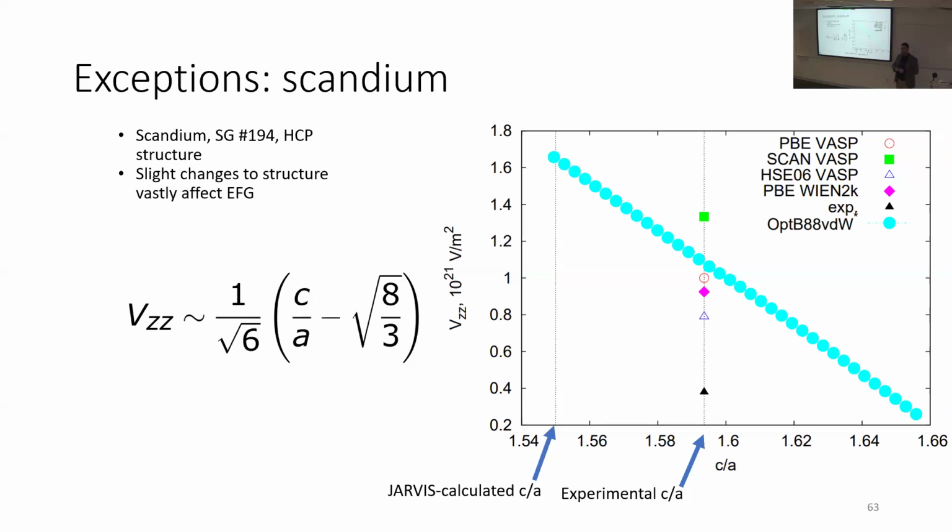What were the parameters in the materials that you were trying to choose? It's a good question. That's a funny question actually, because initially on the project I was using crystal structure data from non-equivalent temperatures, and the values were completely off. Once I moved closer to the temperature range, I started seeing better agreements. But for some systems, yeah, it can totally affect, especially if the crystal structure is totally altered by the temperature. If there's a phase transition, for example, if there's magnetism, for example, it can totally affect the agreement in the system.